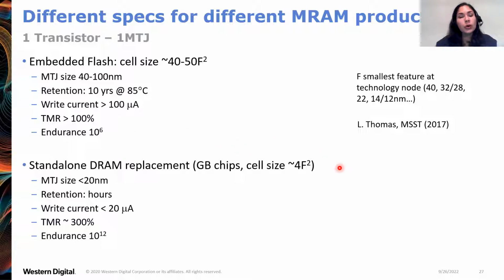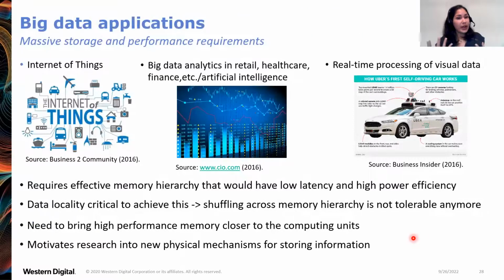If you want to tailor the MRAM for a standalone application, for example, a DRAM replacement, so this is a high density application requiring magnetic tunnel junction sizes that are 20 nanometers and below, write currents that are very small, less than 20 microamps, TMR values approaching 300%, and endurance 10 to the 12 cycles. And the reason why we would want such a high performance memory is because we are now in an era of big data applications that has massive storage and performance requirements.